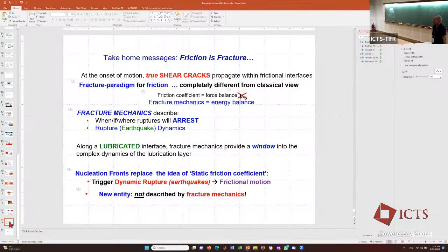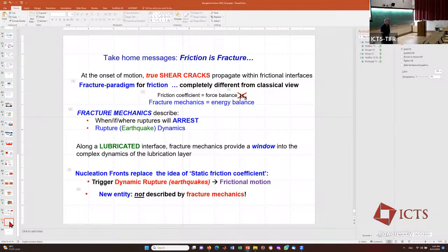Regarding the fracture mechanism you described, there is an initial small crack that propagates. If a system has multiple such cracks, how does the system choose which one to propagate? That's an easy one. The weakest one goes; it's the weakest point that's at relatively high stress. But you can get nucleation at more than one point at the same time, it's just rare. It's a two-body event. You won't see it often because these things travel so quickly. So the first one usually wins, unless it's really, really slow, and then somebody else down the way decides to go at the same time.